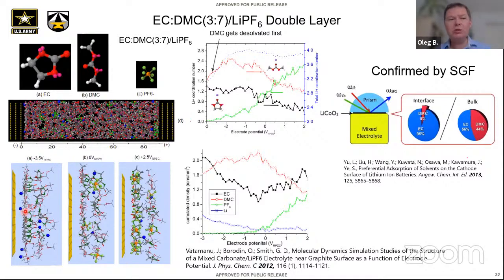And that brings me to an important question. I did publish, as did others, the potential for the dissolution. However, I did it for a neutral surface. And as we polarize it negatively, that potential for dissolution goes down. The free energy for the dissolution changes, and it's actually much easier for the lithium to get dissolved, and it's no wonder, right? We are applying very negative potentials, so it's easier for lithium to reorient and get partially dissolved. Look at the ECs here; they're really standing up like soldiers, right? Very nice alignment. Been in the army, it's all just.